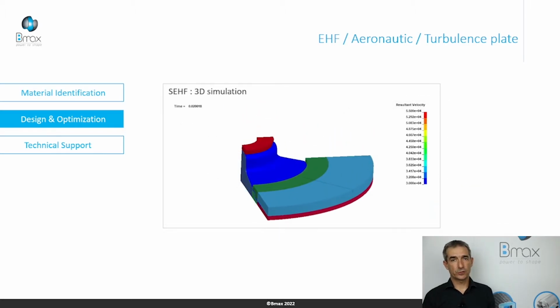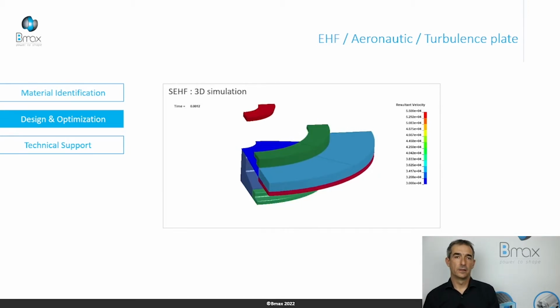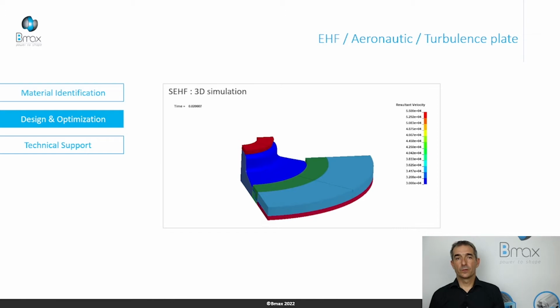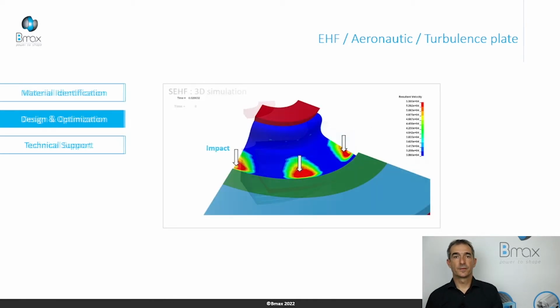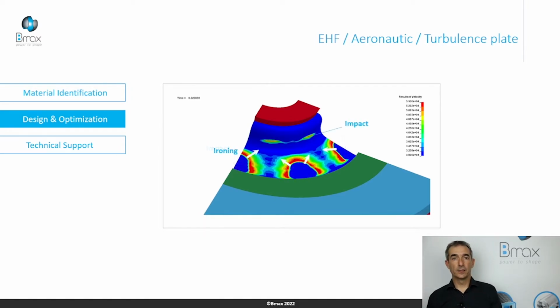The fringe, the colors, represent the velocity of the blank which impacts the die. We can analyze the process thanks to these simulations. The discharge creates a velocity, a dynamic structural response. And with this velocity, we have an impact of the blank on the die, and we initiate an ironing. We create compressive stress. We calibrate the blank, and we propagate these impacts, the contact closings, and the calibrations.